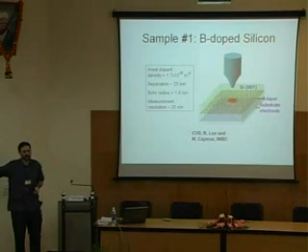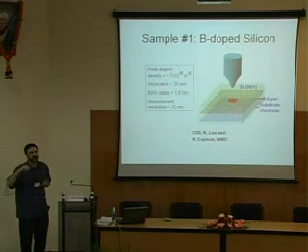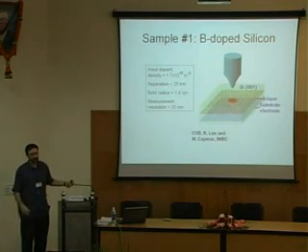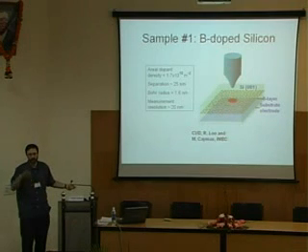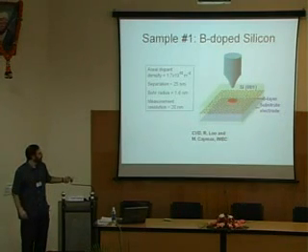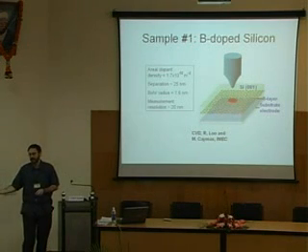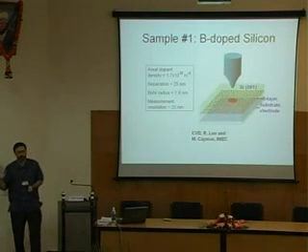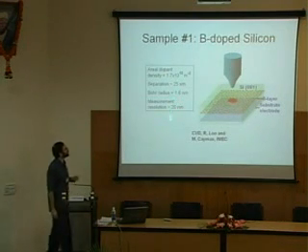STM gets great spatial resolution, but the tip is right on the surface. It's looking at the atoms on the surface. In this case, the atoms are below the surface. A dopant, acceptor or donor, isn't going to act in a nice way if we put it on the surface of the semiconductor. It has to be within the bulk. So the thing that we're trying to look at is about 15 nanometers away, and that means that the lateral resolution, or the sideways resolution, is also about 15 nanometers. We cannot see angstroms like you can with STM. So that is unfortunate.